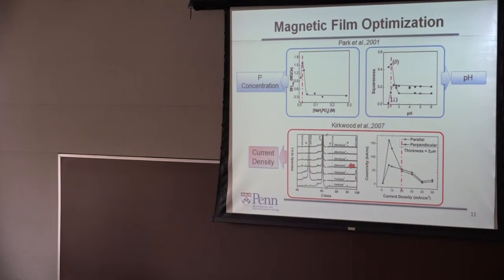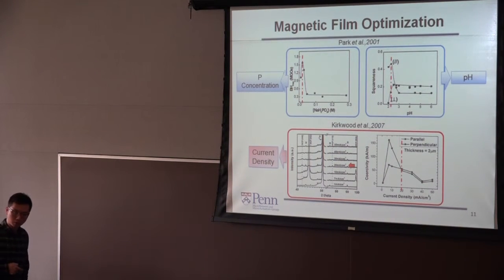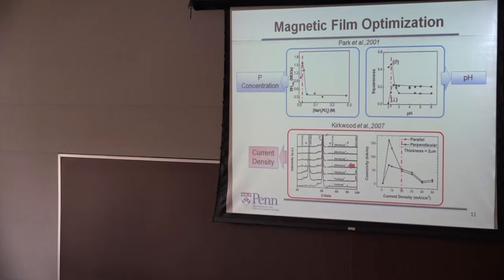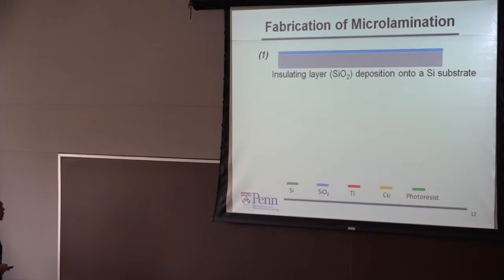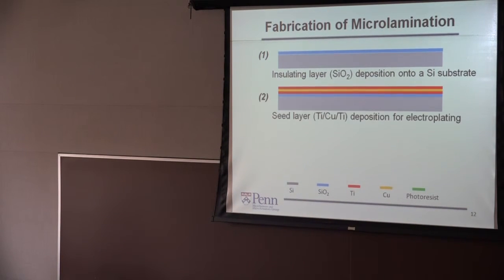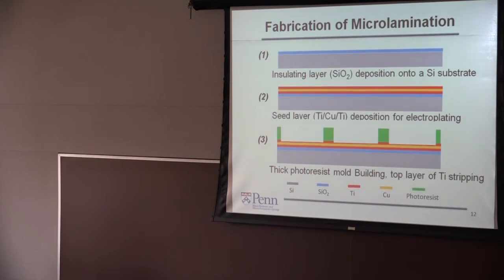The next thing to do is to optimize the plating conditions and bath conditions in order to achieve what we proposed in the material selection guideline. We want a large in-plane energy density as well as an in-plane anisotropy. Based on the existing literature, there are several important parameters we choose to fulfill this goal. For the fabrication part, this is very traditional through-mold electroplating. You have an insulating layer deposited onto a silicon substrate, after which you deposit a seed layer for electroplating. And of course, you have to have a very thick mold in order to plate thick layers.